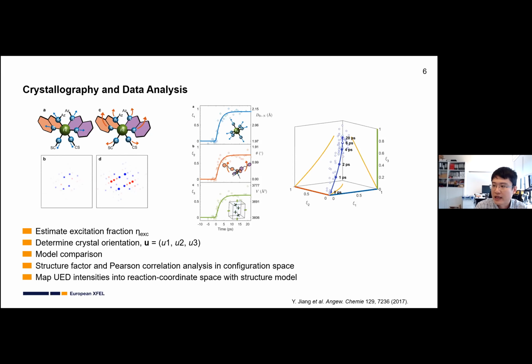So what we do is we set a few key structure dynamics groups because we cannot allow around 100 atoms to move freely and get the structure. So we set 3 key dynamics groups based on the knowledge of chemistry and the knowledge of this sample. For example, for this sample, the first component is iron-nitrogen bond elongation. The second one is the ligand rotation. And the last one is the unit cell expansion. Then we allow them to move towards the high-spin structure or even go back. So we allow them to move.